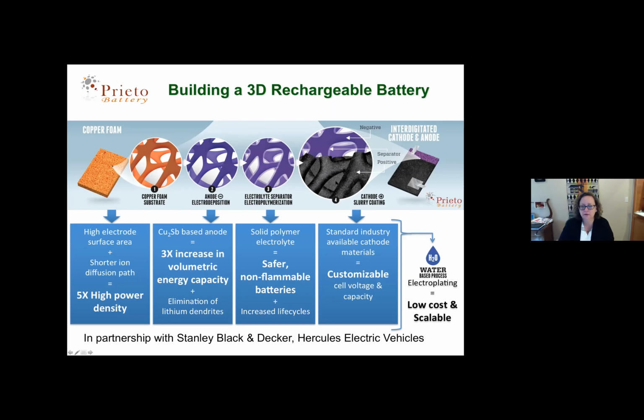And then at the end, we fill in our electrode with industry available cathode materials. We have modified the slurry chemistry a bit so that it is water-based. So the drying process is actually quite important to eliminate water here. And then we apply an aluminum mesh current collector, and I'll show you that in a moment. So our company is very proud of the fact that this is an entirely water-based process. It is very fast. The equipment is really low cost. And we've worked quite a bit on scaling some of the batch yields for the different steps of this process so that we can build larger and larger batteries.